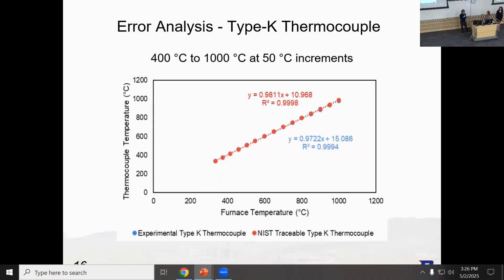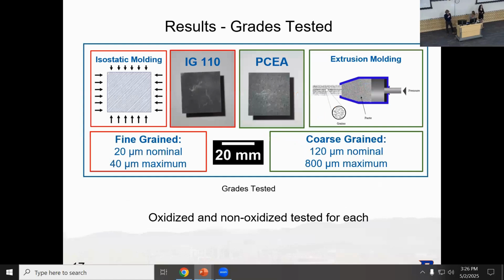Similarly, looking at the Type K thermocouple, we were very pleased to see that there was very little difference between the NIST traceable and our purchased Type K thermocouple. It is worth noting around 850 to 900 degrees Celsius, we did receive a maximum variation on the order of 7 degrees Celsius. However, before this, in the 400 to about 850 degrees range, we did only see a maximum variation on the order of 1 to 2 degrees Celsius.